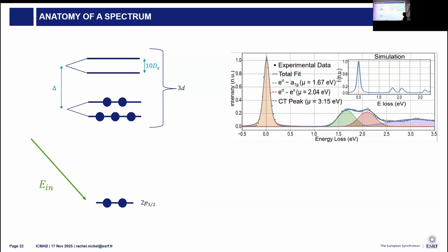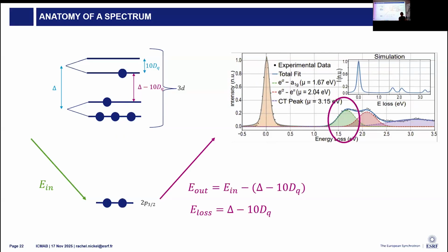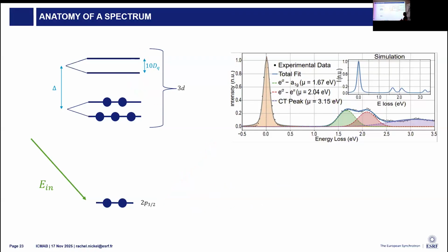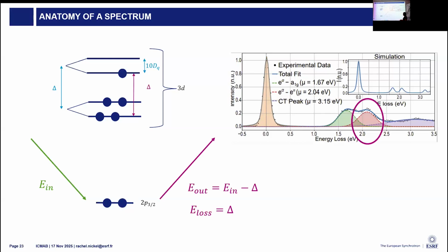Slightly more complicated, we have our excitation to that same empty state, but the electron that falls down is from a different orbital. And this leaves our final state in a slightly excited position. And we can measure the energy loss, which gives us the exact orbital spacing between these levels. Same process for the second feature where we excite up and it drops not from the higher eg orbital, but from a lower t2g. And we get, well, there's a splitting here, this exchange coupling interaction.